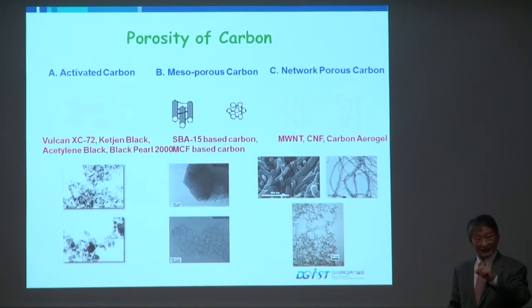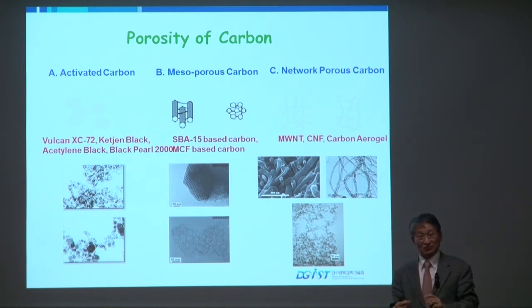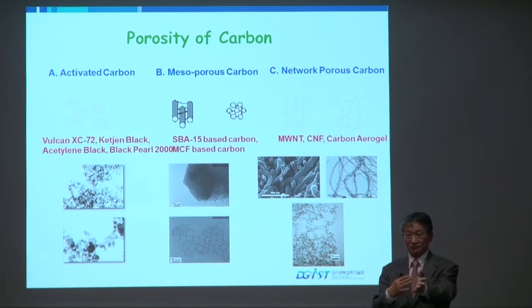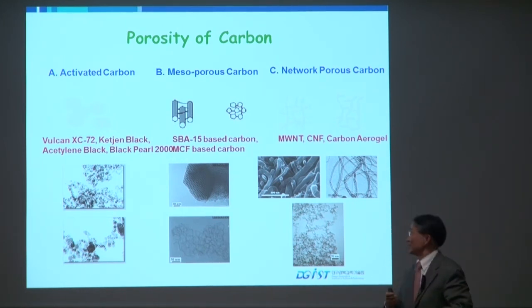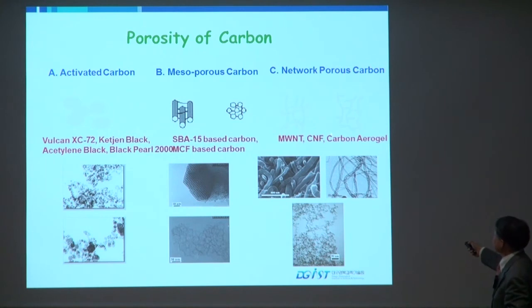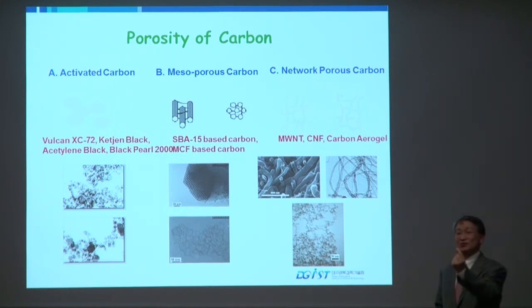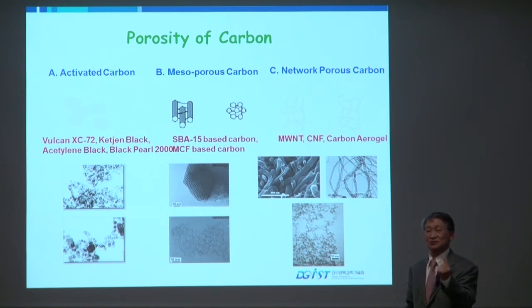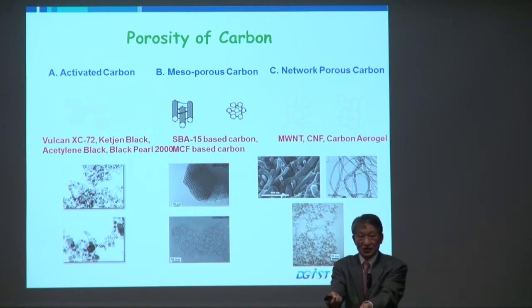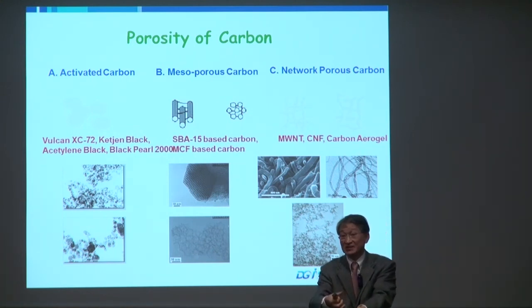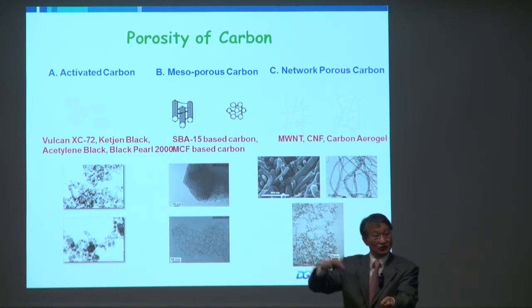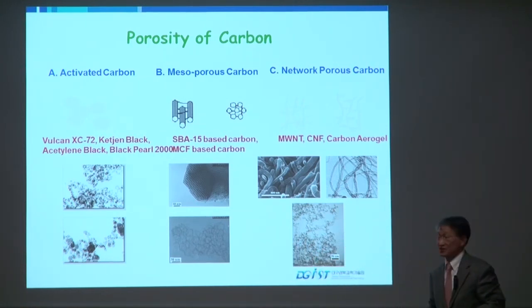And porosity, and this is the third time I'm mentioning porosity, due to the transport of the reactant, is also important in fuel cell reactions. Carbon nanotube is, of course, a diameter in the order of angstroms, less than hundreds of angstrom, which is very, very small pore sizes. But in the bundles of these carbon nanotubes, between the carbon nanotubes, there are secondary pores, which are pretty big in size. So that's where the reactant passes through.